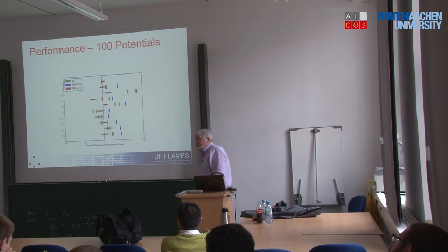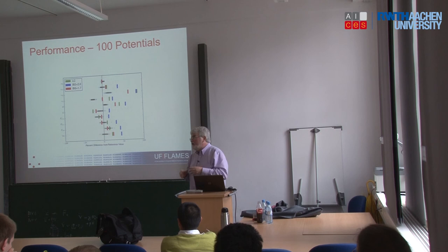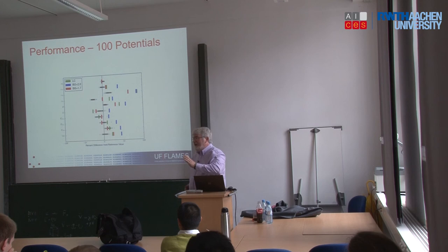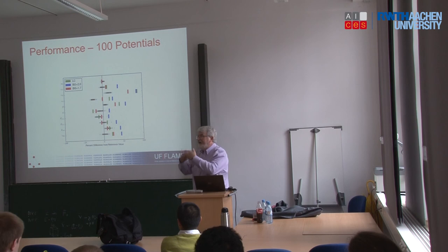You can put in some phonon information. You can put in frozen phonons, for example. You could put in a zone edge phonon and put the energy of that in. As you know, you've got the gamma point, you've got the line, because that's the elastic constant. That means you're going to roll over to the right value, so you're going to get most of the phonon structure right. But that's not the harmonic part. Getting the anharmonic part is difficult.